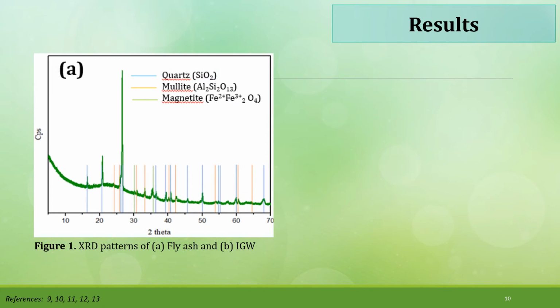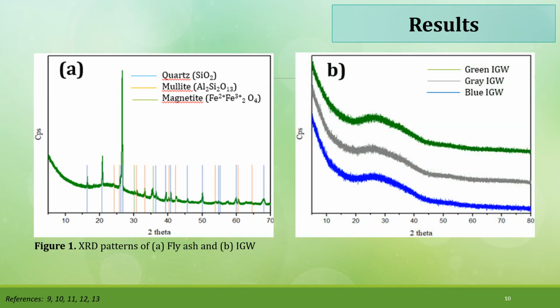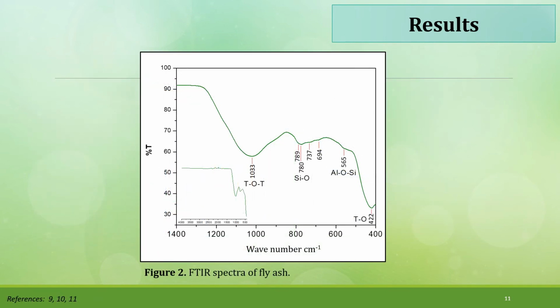X-ray diffraction analysis of the fly ashes confirmed the presence of amorphous material, identified in the diffractogram by the lifting of the baseline and the wide halo of 15 to 35 degrees of 2 theta. Likewise, the characteristic signals of quartz, mullite and magnetite were observed. The presence of amorphous material in a higher proportion is an indication of the reactivity of the fly ash, which is important for the activation of the fly ashes in an alkaline medium. XRD analysis of the glass confirmed its amorphous character or low structural order, without the presence of crystalline material. The 20 to 40 degrees wide halo of 2 theta in the diffractogram is characteristic of its amorphous nature. Its position and maximum intensity are related to the calcium content present in the glass.